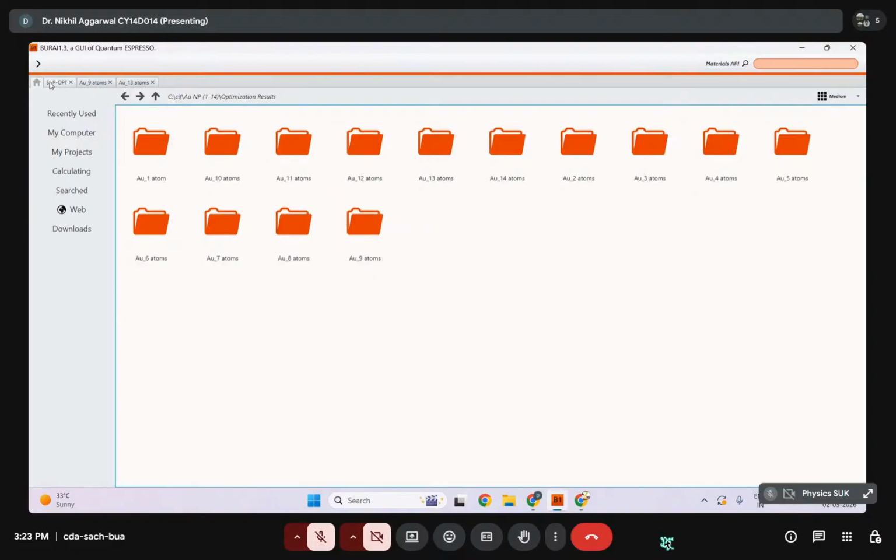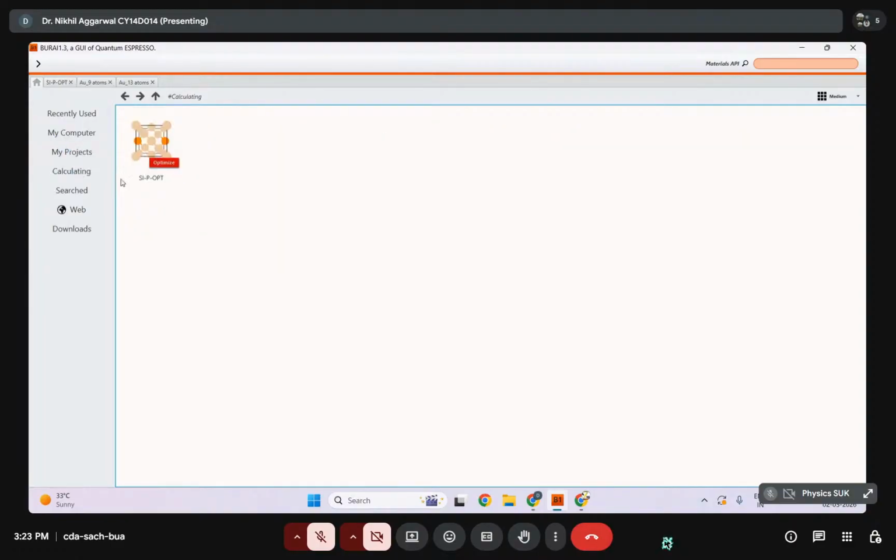I'll consider the silicon phosphorus optimization result if the calculation is over. It is still running. The optimizations are time-consuming calculations. Meanwhile, I'll move on to the next part, which is the designing of these kinds of nanostructures. Regarding the structural optimization, I discussed the substitutions, the delta E and the delta F condition. Delta E acceptable up to -3, delta F acceptable up to -2. Correct. And as and when the optimization is done, I'll discuss the result part of it.